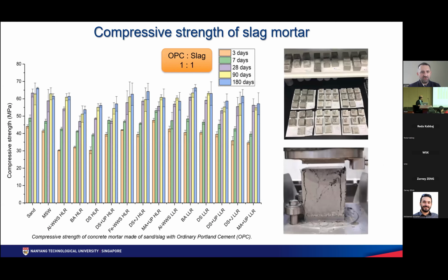We also investigated the use of the slag in mortar together with OPC to see how it behaves in terms of the strength, compressive strength, to evaluate its use for non-structural and see if it could possibly be used for structural applications. So you have from here down all the mixes that we investigated. We compare ourselves to the slag which was developed only from municipal solid waste, as well as typical mortar of OPC and the sand. So you can see that this graph is relatively boring, but in this case, boring is good because as compared to sand, the slag ultimately performs in a similar way if given a slightly longer curing time.